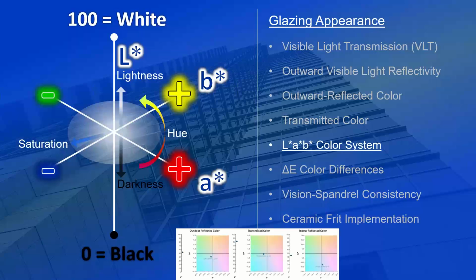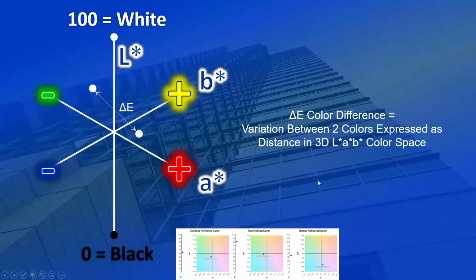Your hue color is where that glass sample falls in the A star, B star axis. And saturation is how far away from the center or origin point that sample falls. And then lightness, of course, is the vertical L star axis there. The delta E is a combined number that we use to look at the color variation between glass samples. And we can provide delta E's for outward reflected color, for transmitted color, and indoor reflected color.